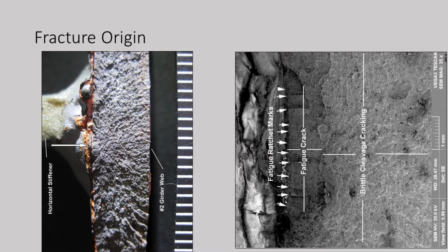That's interesting enough, but the other thing of interest is this. This is the scale that sizes our details that we're looking at. That's 1 millimeter. So what we're seeing here is a thumbnail, which is a fatigue crack, that is 1 millimeter deep and 5 millimeters long, and that's the critical crack size to instigate unstable brittle fracture. Because when that happens, boom, that big crack appears really quick. That small fatigue crack may take a long time, like 60 years, to get to that point.